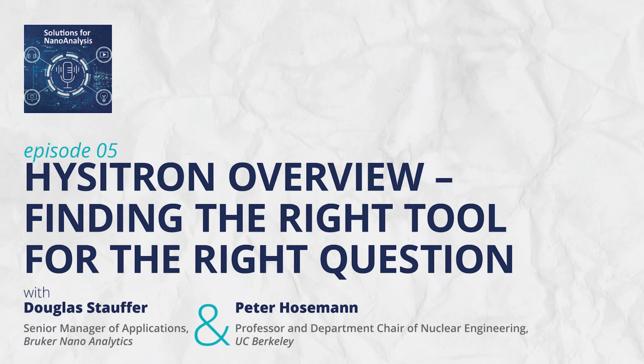Yeah. I noticed that you're very interested in micromechanics and not necessarily going down that one more length scale to the nanomechanics, where if your sample size has 0 free dislocations, then your yield strength is nucleation of dislocations. Or if you have existing dislocations, then they run to the surface. And then again, you're back to nucleating dislocations rather than moving them. So that's very different than how a bulk metal deforms. Right. Well, yeah, that's right.